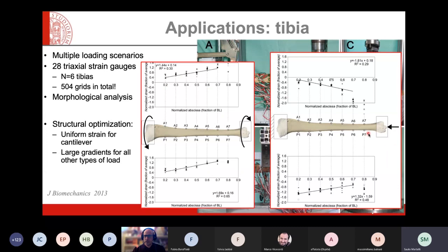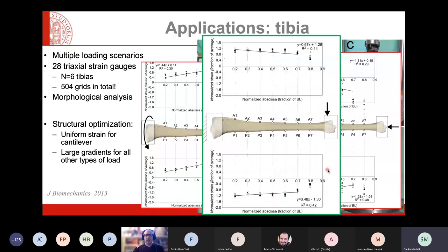Here you see that for torsion and axial loading, there are large strain gradients all along the tibia, so different strain values. And conversely, when a cantilever load is applied, the stress and the strain are amazingly uniform. Now, this loading condition corresponds to the anteroposterior force that you deliver to the tibia during walking. So this confirmed the hypothesis that this is a uniform stress structure optimized to have minimal amount of material with a constant safety factor all along the bone.